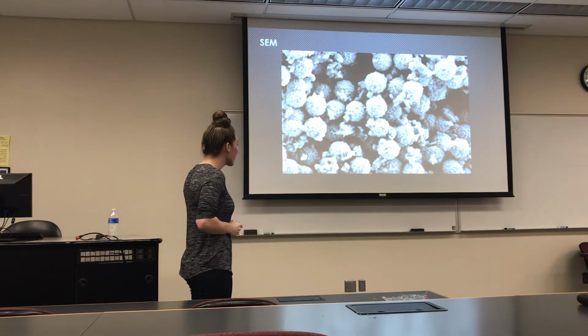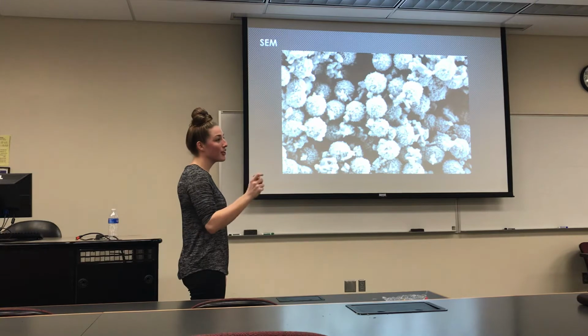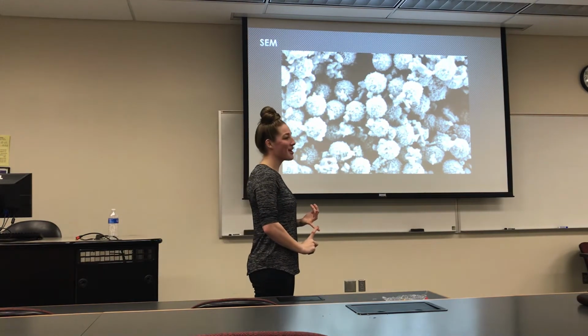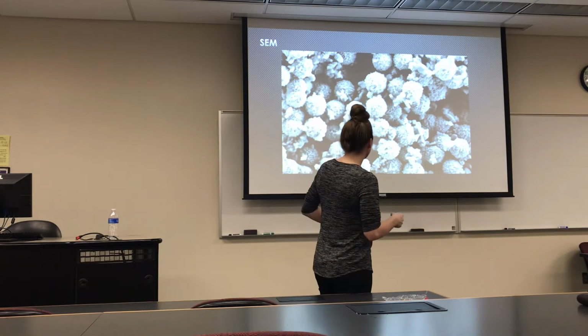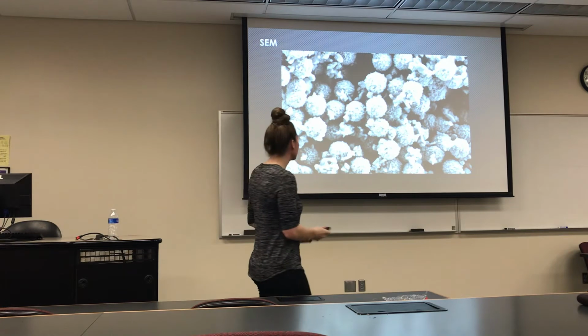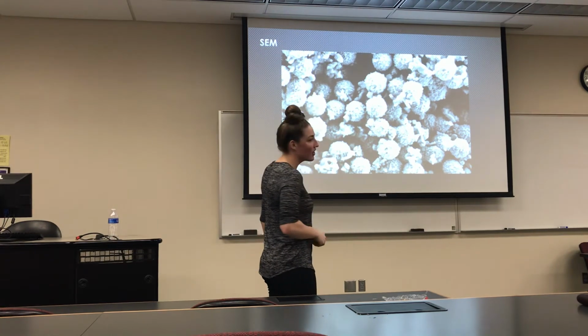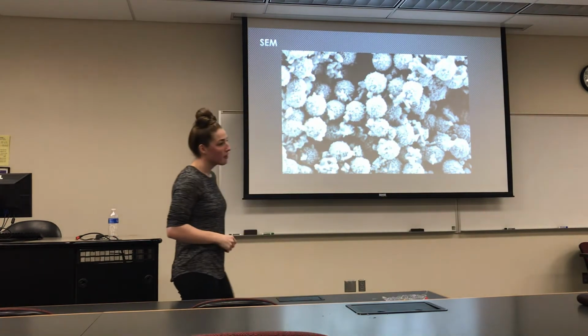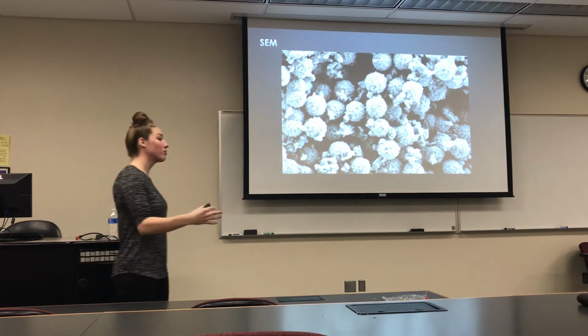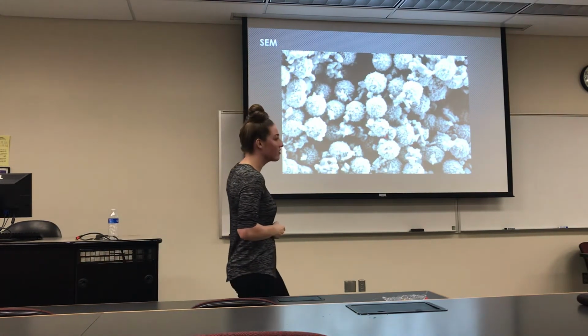But I also got a lot of these colloidal palladium nanoshells in solution, which is what I didn't want to happen. That was unbound. So we probably want to lower that concentration and do multiple reductions, so we're just left with this palladium nanoshell structure instead. Right. Yeah. So that was one of the issues. That's primarily why we had to do the multiple reductions with the gold, so we didn't have this happen.